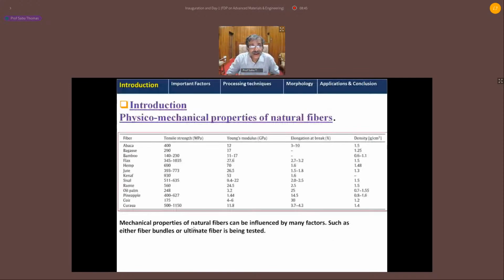Let us look at the mechanical properties of this material. These materials have very good mechanical properties. Look at tensile strength, Young's modulus, elongation at break. Interestingly, if you look at the density of this material, the density is always 1.5, 1.25, 1.1, much lower than glass fiber. Therefore, the specific properties, property divided by density, these materials give fantastic values. It can beat glass fibers.